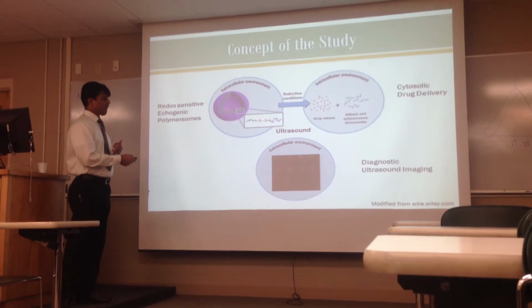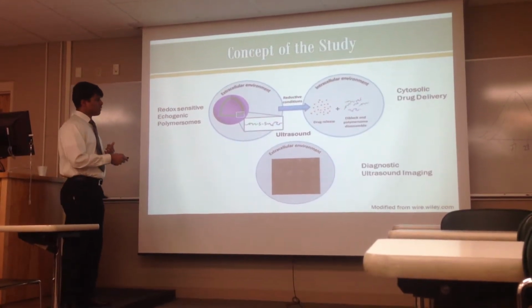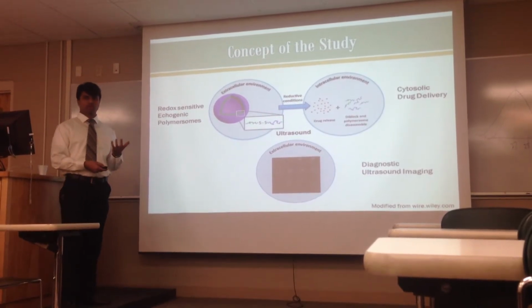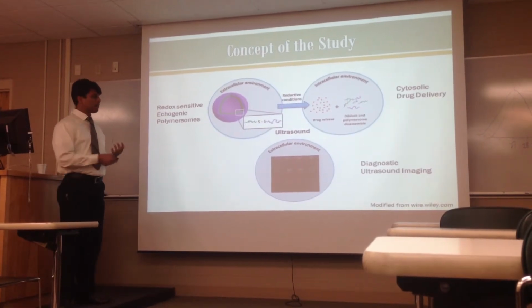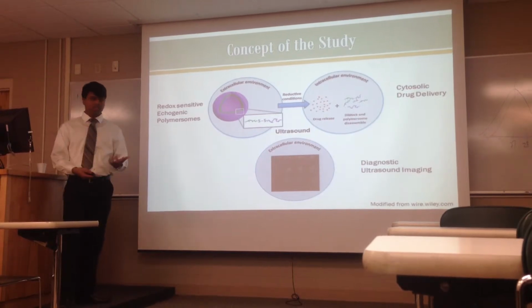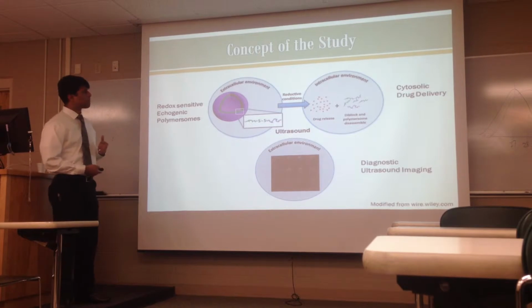So the concept of the study is to prepare echogenic polymersomes which will have a disulfide bond between the two parts, the hydrophobic and hydrophilic part. So when these polymersomes enter the cytosol, where there is a high concentration of thiol, they will release the content with simultaneous ultrasound application, and we'll also have ultrasound imaging when these polymersomes circulate in the extracellular environment.